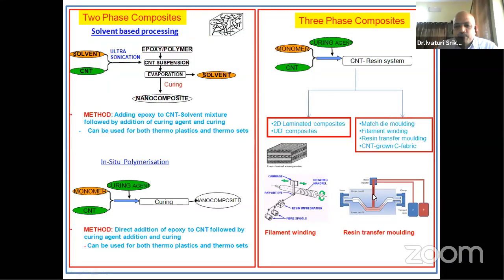Similarly, if you mix the CNTs into the resin system and try to impregnate that filler-added resin, the liquid resin can infiltrate and wet all the fabrics across this thickness. There may be some 20 layers. Resin can infiltrate, but all the fillers that you are adding into the resin system will just settle on the topmost layer, because the topmost layer acts as a filter. So that is one of the disadvantages with nanomaterials in terms of processing.